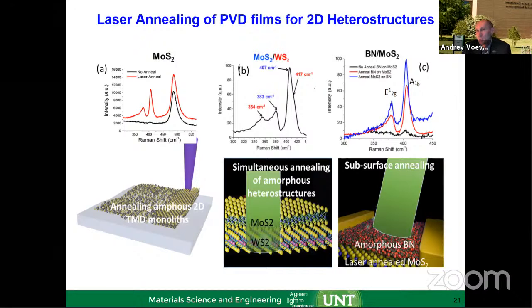So we're doing these experiments now. Hopefully we can share some results, but the first results were done years back, where you can anneal through the boron nitride on MoS2, and you're annealing it, that red curve, and you can see the molybdenum disulfide peaks coming up and the boron nitride. So that seems to be one of the ways of doing that.